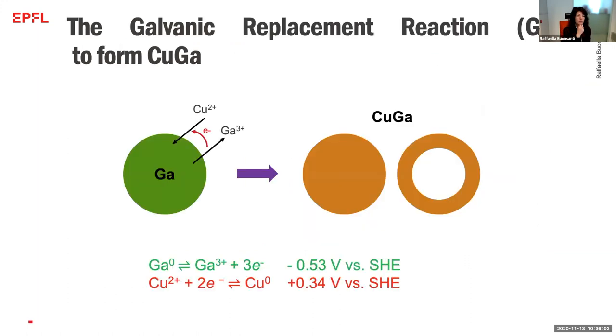And we decided to rely on a reaction that is very well known for noble metals. The nanocrystal community has studied this galvanic replacement reaction very well. Based on what is known, we were expecting that gallium would behave like other metals, and that, because of the redox potentials of these two metals, in the presence of copper 2 plus, the gallium would oxidize while the copper would reduce and eventually form copper gallium alloys.